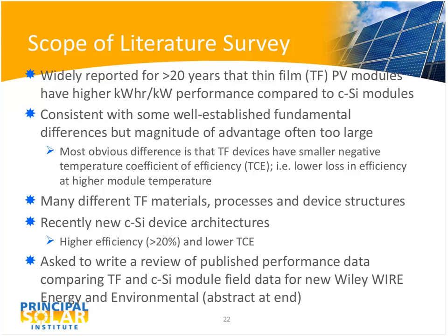And the most obvious difference between the thin films and the modules and crystalline silicon is the temperature coefficient of efficiency, which Matt alluded to as one of the parameters that they include in their modeling. I refer to it here as TCE, temperature coefficient of efficiency. Thin film, it's always negative, which means module performance always goes down as the module heats up, but thin film modules decrease less. In other words, they have relatively better high temperature performance than a crystalline silicon module.